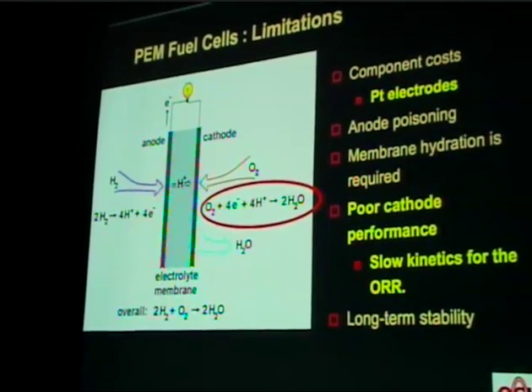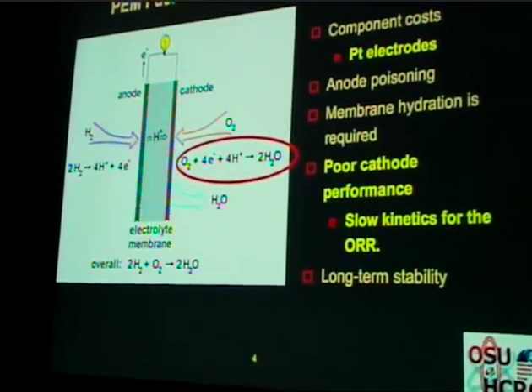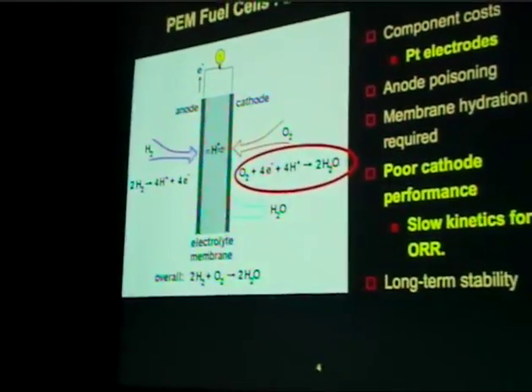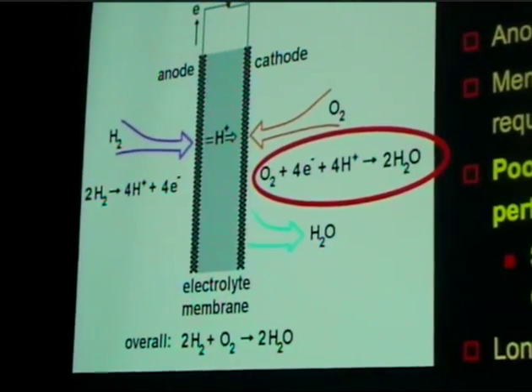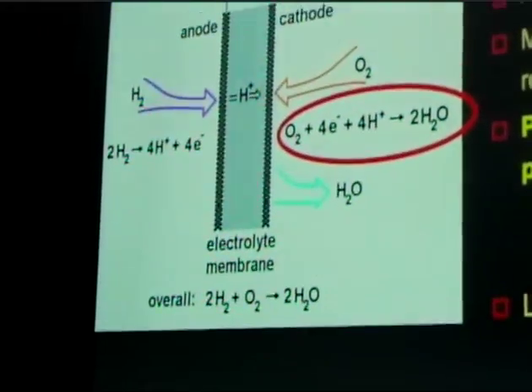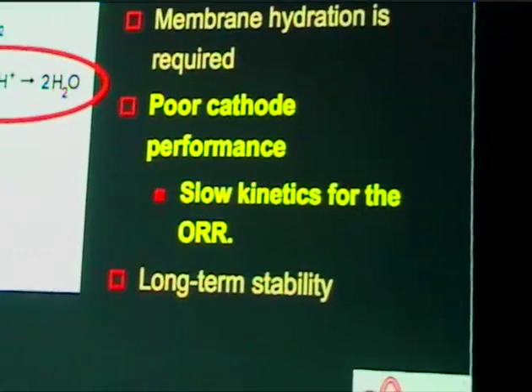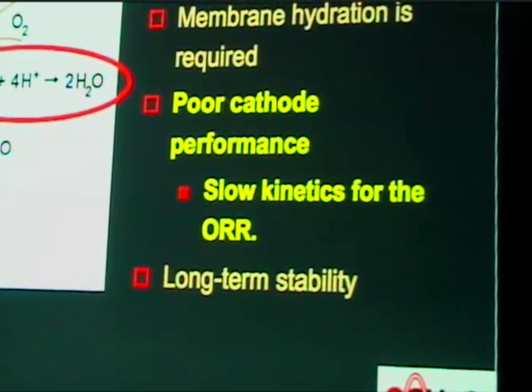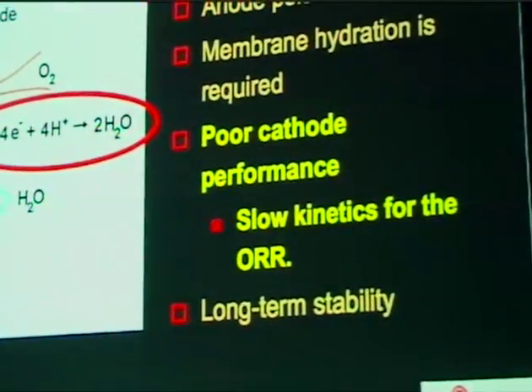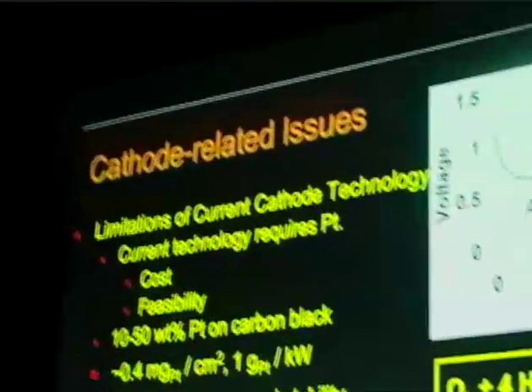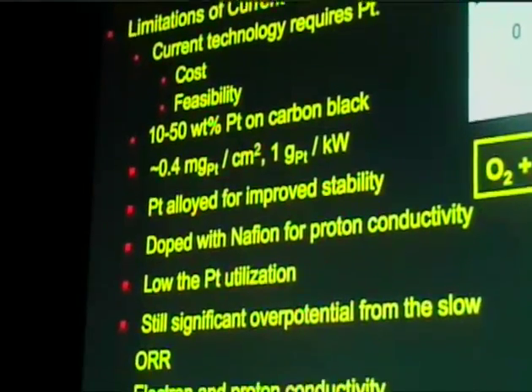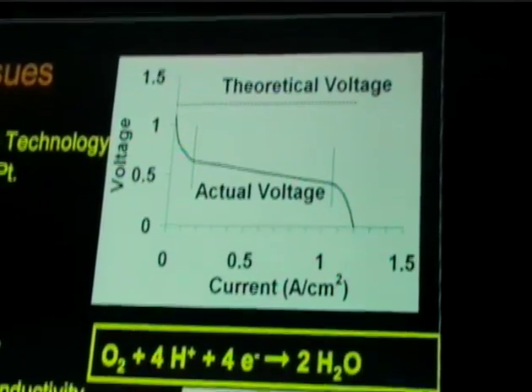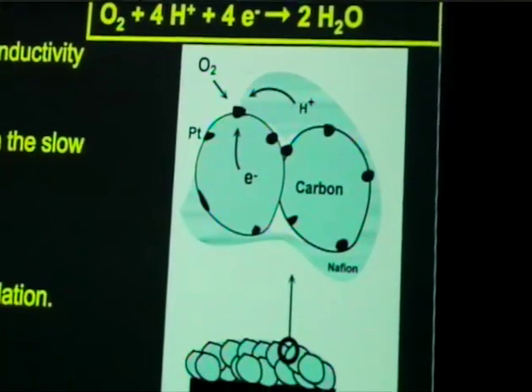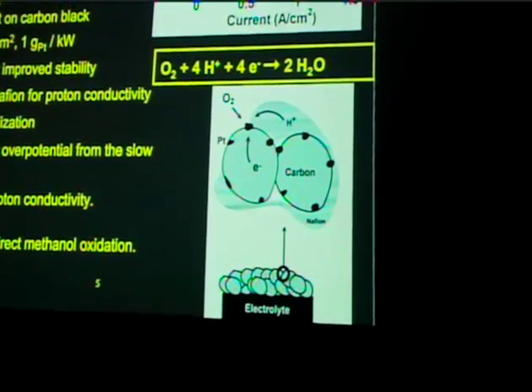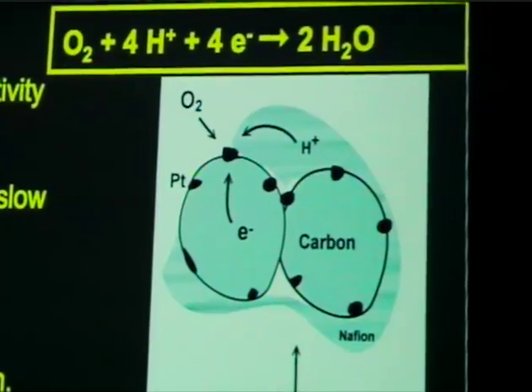Now, if we look at the current technology, we see that current technology is really relying on platinum electrodes on both sides. We have issues with the anode poisoning because of CO, even very low CO concentrations in the hydrogen streams. Membrane hydration is required, and then the cathode performance is still limited because the temperature really makes the kinetics very slow, and long-term stability still is one of the limitations for this technology. Now, if we look at the current technology on the cathode side, as I've said earlier, platinum is the catalyst. Obviously, the cost and feasibility are very important. Again, if we look at the required platinum, if we try to convert a good portion of the cars to PEM fuel cell operated cars, we may replace dependence on foreign oil by dependence on foreign platinum.